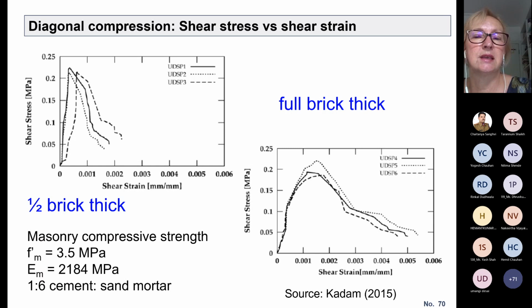In this case, we got 0.2 to 0.3 megapascals, and the compressive strength of masonry in this case was 3.5 megapascals. So you can see roughly that the shear strength is less than 10% of the compressive strength. And we will use shear strength for determining shear resistance of masonry walls. And these specimens, just for your information, are made from this M1 mortar, which is 1:6 cement mortar. This is the PhD thesis of Kadam from 2015.